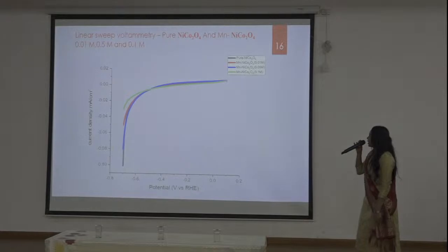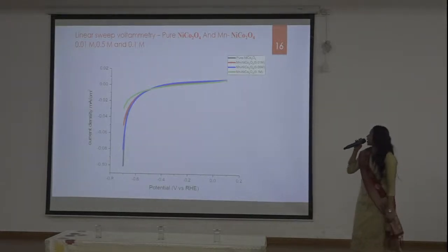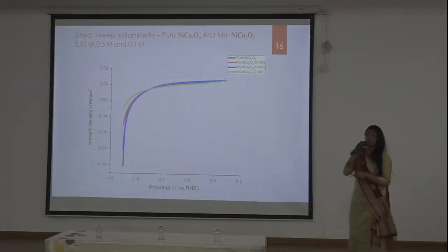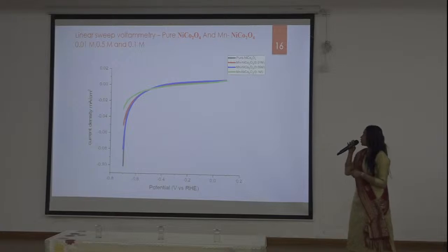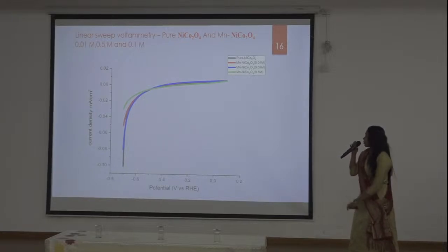So this is a LSV curve for pure nickel cobalt oxide and manganese doped nickel cobalt oxide for different ratios, which is 0.01, 0.05, and 0.1 molarity ratio.